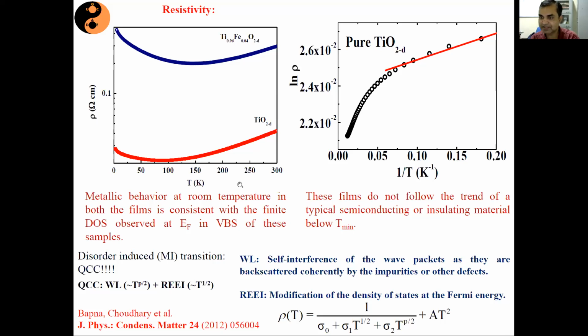How do I confirm that they are conducting or metallic? Just by looking at this temperature profile. If you are decreasing the temperature, the resistivity is also decreasing. This is the characteristic of a metallic system. What is the characteristic of a semiconducting system? If you decrease the temperature, the resistivity increases. Why? Because as you lower the thermal energy, the chances of electron excitation from valence band to conduction band decrease. And therefore, your resistivity keeps on increasing with decrease in temperature for a semiconductor. Or in other words, for a conducting or metallic system, we have a positive temperature coefficient of resistance. Temperature coefficient of resistance means 1/R dR/dT.